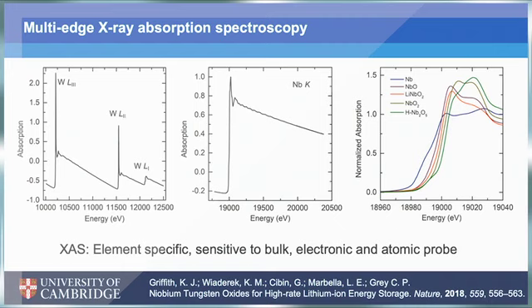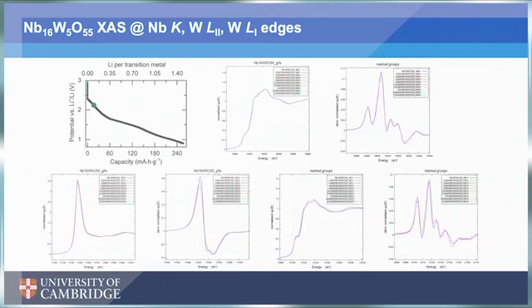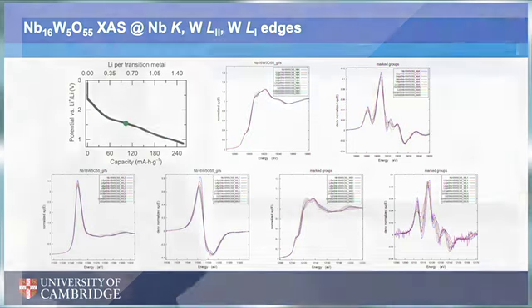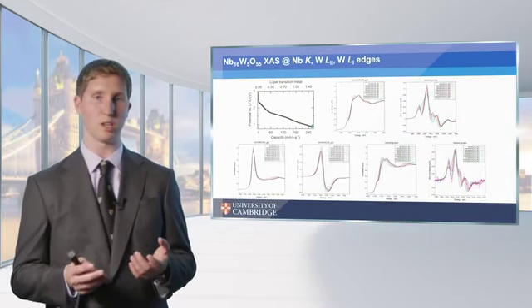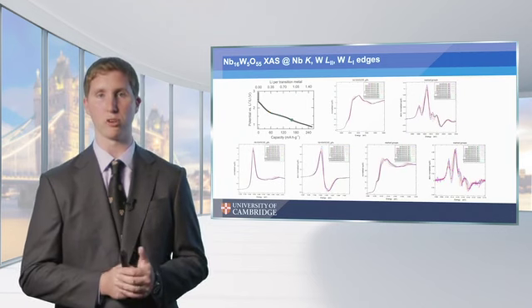We're probing not only the electronic structure and the oxidation state, but also, as I mentioned, that local atomic structure. And so in this example here on the crystallographic shear phase, and there are analogous data for the Nb16W5O55 bronze, what we see is that as we move down as a function of discharge in the half cell, so this is lithiation, as we increasingly lithiate the materials, we're moving from D0 niobium and tungsten nominally to D1, and then in our multi-electron redox even D2 electron counting. And so that should be associated with an edge shift, which we observe. And the other subtlety in these materials is that when they're D0, they experience what's called a second-order Jahn-Teller effect. This second-order Jahn-Teller effect occurs when there's a pseudo-degeneracy between the filled p orbitals and the empty d orbitals in these early transition metal oxides.